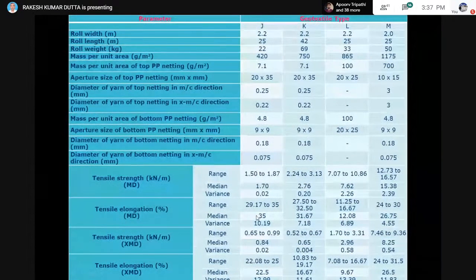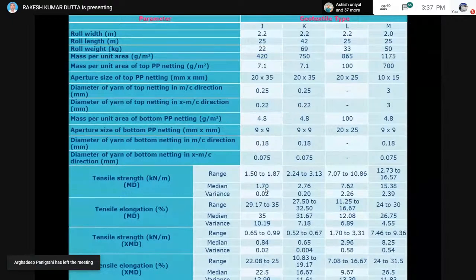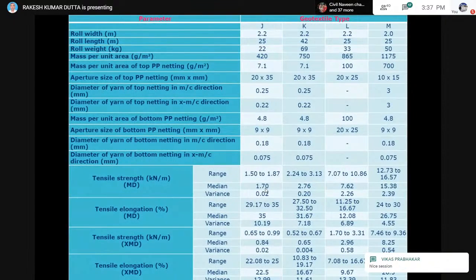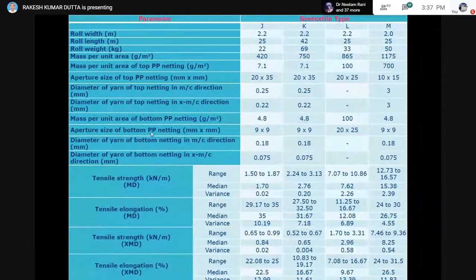So the procedure followed is similar, but the strength you are getting is very less. And this lesser strength is basically because in the case of non-woven material, the loose web doesn't have the strength. The entire strength comes because of the scrim which we provide, because of the netting we provide, because of the stitching which we use in one particular direction. So all these parameters contribute to the tensile strength of these non-woven kind of materials.